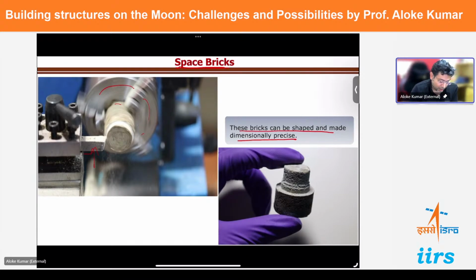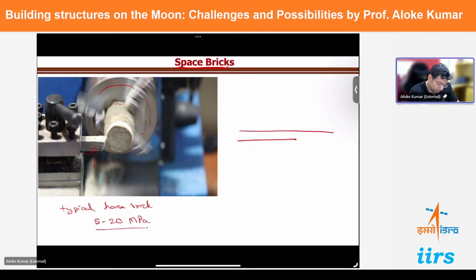By the way, your typical house brick, okay, typical house brick is usually somewhere between 5 to 20 megapascals strength. Okay. Megapascals is the SI unit. Mega is 10 to the power 6. Pascal is the SI unit of pressure. So 5 megapascals is the compressive strength of this particular type of brick, the whole house brick. But we had reached some 2.5. This particular research, as you saw, this was published quite long ago.